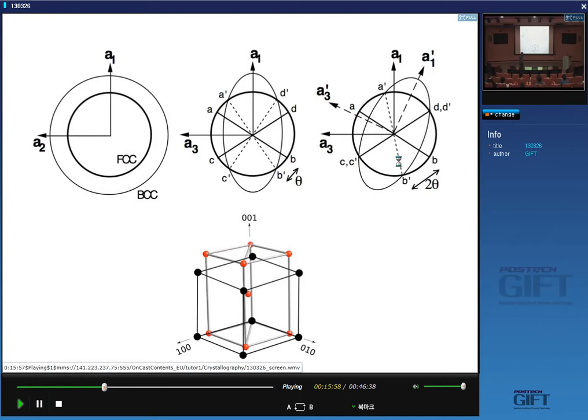Now, supposing that I do my Bain strain, and then I rotate the ferrite with respect to the austenite. So I add another deformation which doesn't alter any length, but it rotates the crystal. And here is one such rotation where I've added a rotation to the Bain strain so that one of these lines becomes coincident with the other. Then I can produce one invariant line.